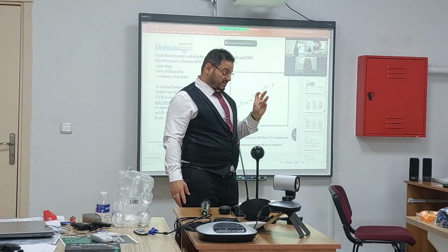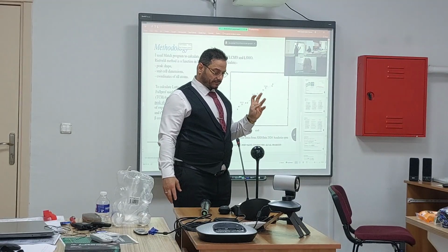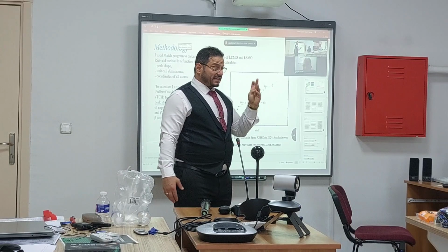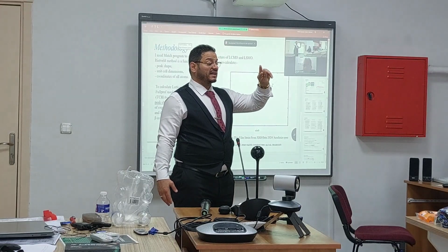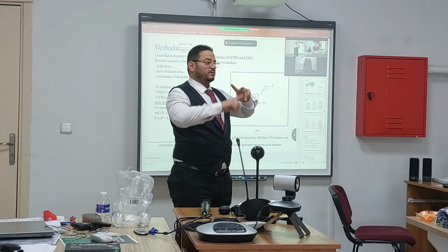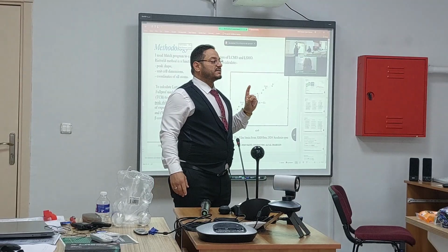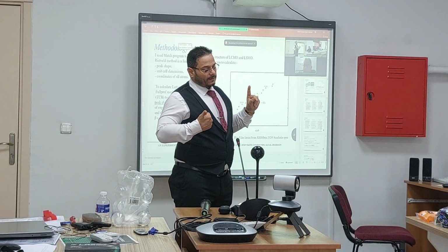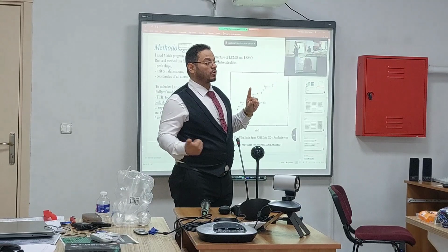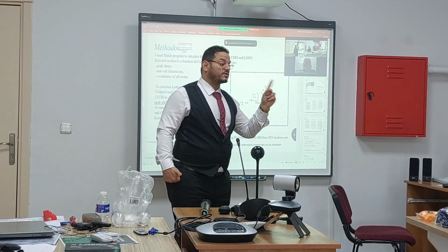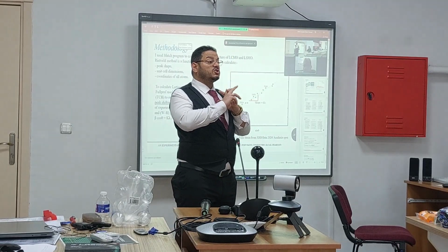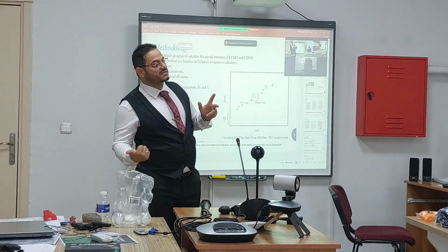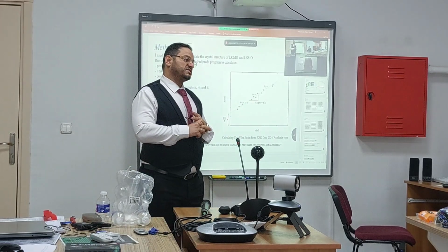By using these process agents, there are two advantages. First, it avoids the cracks that could appear in my structure during the drying process, and second, I can increase the particle size of my perovskite oxide.